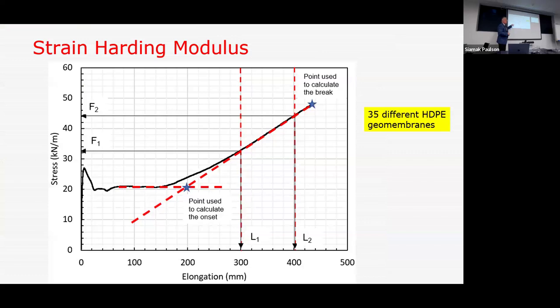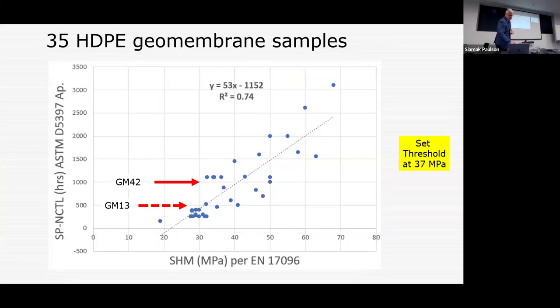And you'll develop from this a load deflection plot. And you're very interested in the slope of this tail end of the curve. Okay. The steeper the slope, the better the stress cracking resistance. Okay, so as steep as you can make that, the better. This is 4 years worth of work. So this is a correlation between strain hardening modulus and single point notch constant tension load.